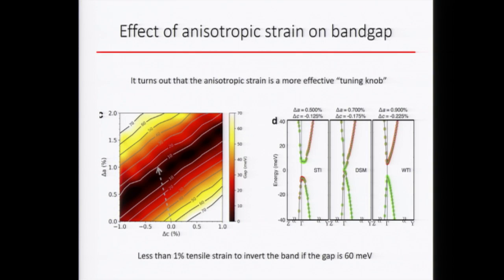Okay, the previous calculation I showed you was calculating the band structure as a function of isotropic expansion and contraction. So we asked our collaborator to calculate the band gap as a function of A lattice constant strain and C lattice constant strain. It turns out the band gap has a very anisotropic response to the strain. The black corresponds to 0 gap and the white corresponds to maximum gap around 70 millielectron volts.